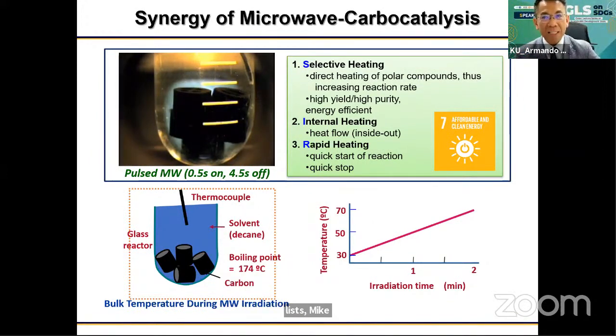Microwave is applied instantaneously in only 0.5 seconds. It's off for 4.5 seconds. And you can see bubbles forming. There is a thermocouple measuring the temperature of the solvent, which is decane. There is a carbon material. Decane, carbon, the thermocouple to measure the temperature. Microwave is irradiated in only 0.5 seconds and it's off for 4.5 seconds.